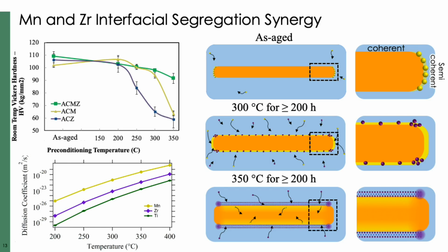Overall, the addition of manganese is necessary in order to stabilize the microstructure for a long enough period of time for the slower diffusing zirconium and titanium to segregate to the coherent theta prime interfaces and eventually form an L12 structure. The formation of the L12 structure further reduces the interfacial energy of the coherent interface and also creates a ledge poisoning effect, which ultimately further stabilizes this alloy.